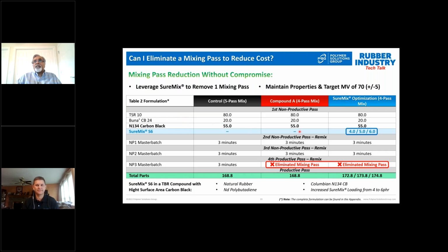So what we did is we mixed in a 4-pass as is, no change to the formulations, and then we looked at 3 different levels of SureMix and asked, what would be the ideal level for this application where we can meet the performance and the processability requirements?